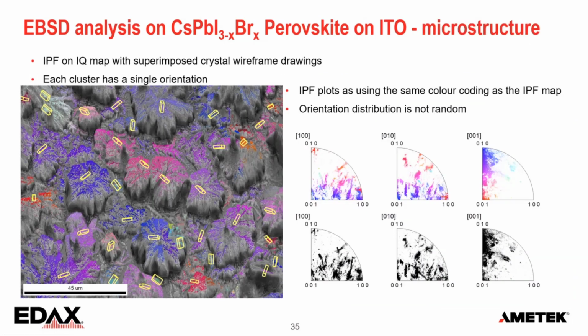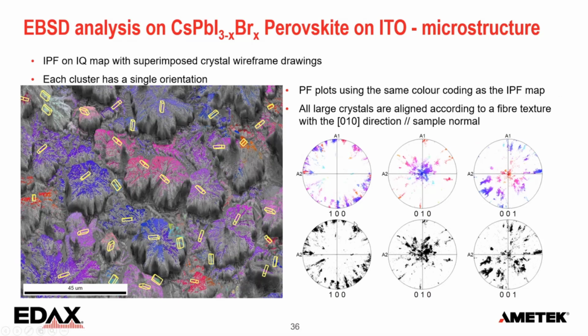And even nicer, when we look at the orientation distribution, when we take inverse pole figures, there's not that many grains, of course, but you can see it's not random. There's a very clear girdle here in the 010 inverse pole figure. The other ones are a little bit less clear, but it's away from the 010 direction. And when you color code that, you can correlate very easily all the points in the pole figures with the map. And here in the normal pole figures, the structure is more pronounced. It's a very clear 010 centering where the other directions are around the edge of the pole figure. So it's almost a fiber. Not completely, the 001 looks a little bit different, but you can see what is happening, where each cluster has a single orientation.